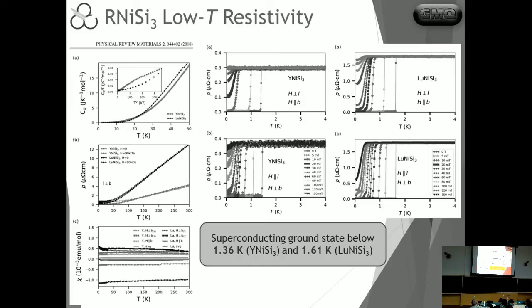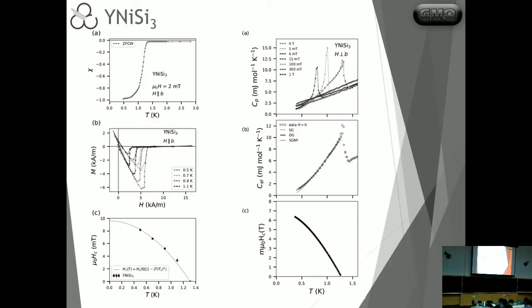And nothing special came out here. But when Fabiana went there and started measuring at low temperatures, we could see that just hiding there were these two new superconductors. And they're not just two new superconductors, but there are some interesting things happening here that are worth further looking into. So first of all, notice that we are talking about a ternary intermetallic system, and it turns out, if you look, for example, here in the magnetization curves, that this is clearly a type 1 superconductor.